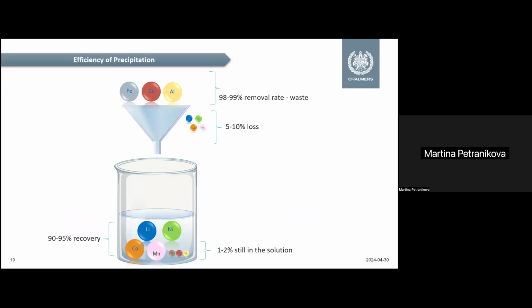When it comes to the precipitation, the efficiency is usually also quite high, so we can remove from 98 to 99% of the impurities. What is maybe good to remember is that very often in this step, we have some loss of the transition metals. That depends on the technique or how effective the process was, but the loss can be from 5 to 10%. So then after the removal of the impurities, we have our transition metals plus lithium still in the solution, but if the process wasn't completely effective, then we still have some small impurities in the solution.